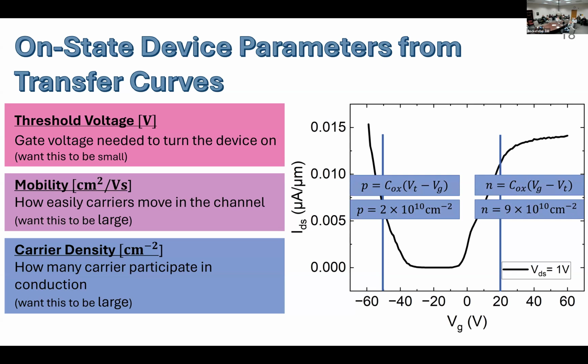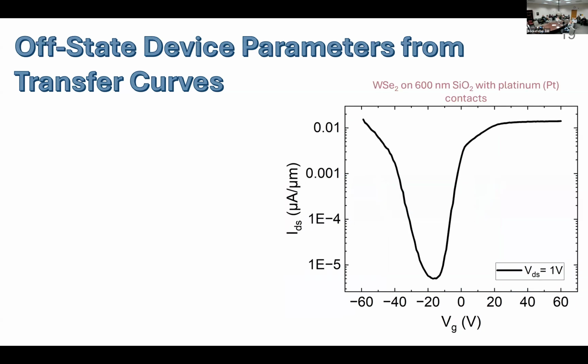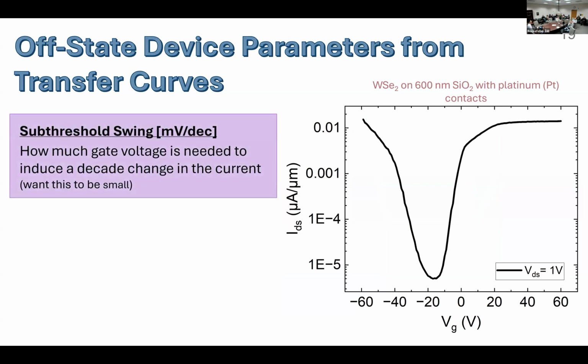We can also obtain values of device parameters in its off state by looking at the semi-log plot of this graph. So one of the device parameters that we can obtain is the subthreshold swing, which is how much gate voltage is needed to induce a decade change in the current. This is kind of a measure of how good your device is at switching. So ideally, you would want this to be very small. You don't want to have to apply a large gate voltage to turn your device on. The way this is calculated is looking at the smallest off current and the onset of threshold current. So if you recall from the previous graph, the threshold voltage for this device was around -5 and -45. So that's where I drew this line.